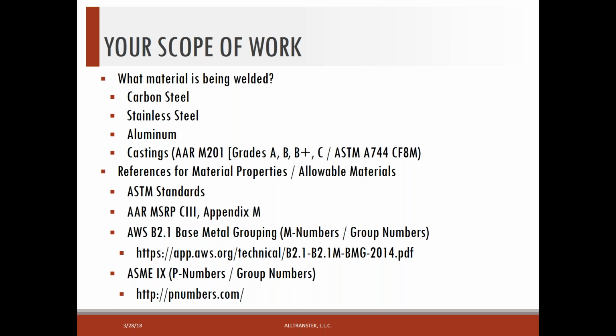That's the reason for grouping these materials, both under AWS B2.1 and also in ASME Section 9. We have the same system with P numbers and group numbers. And in almost all cases, an M number identified by AWS specifications will be the same as a P number identified in the ASME material grouping. In other words, an example of that would be A516-70 material. It's considered a P1 material in the ASME Section 9 system, and it's considered an M1 material in the AWS base metal grouping. So usually the P number will correspond with the M number. And then group numbers are typically only used when notch toughness requirements are imposed.